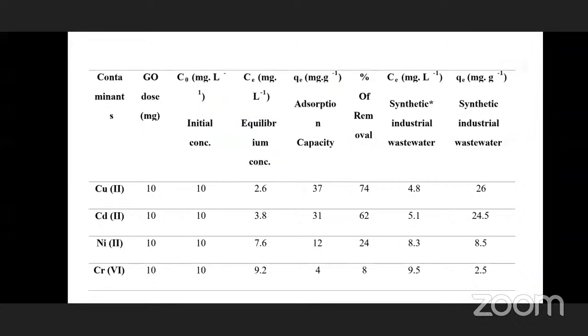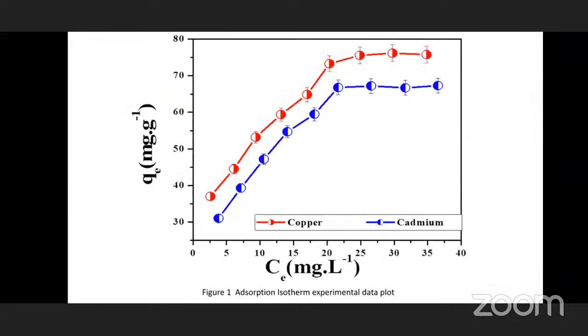For these 4 metals, we have seen that 74% of copper 2+ ions can be removed by this graphene oxide, 62% of cadmium 2+ can be removed, nickel only 24%, and chromium only 8%. So copper is removed in the highest percentage by this graphene oxide. For other heavy metals, we will study in the future. And this is the graph for the removal of heavy metal ions, the adsorption isotherm experiment data.